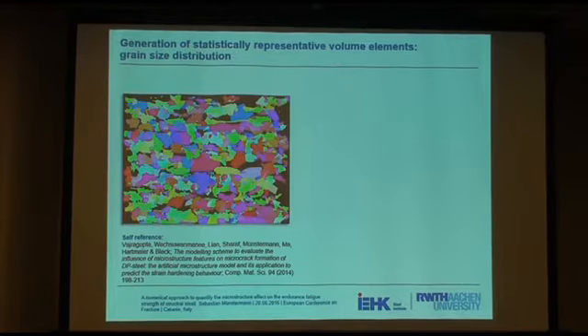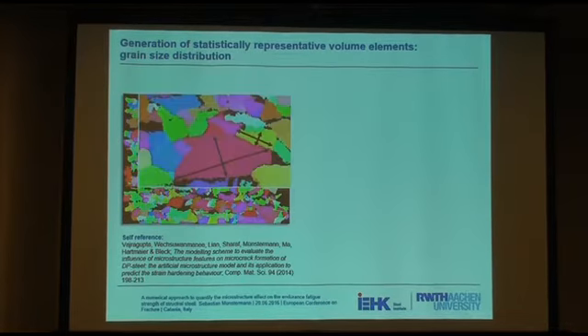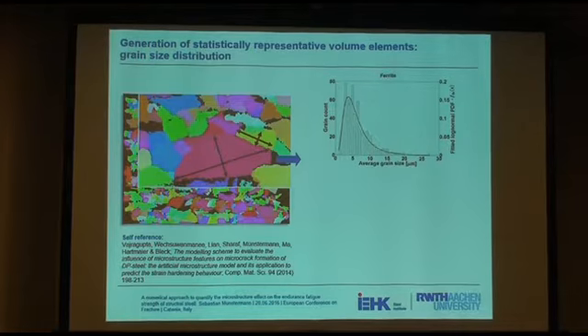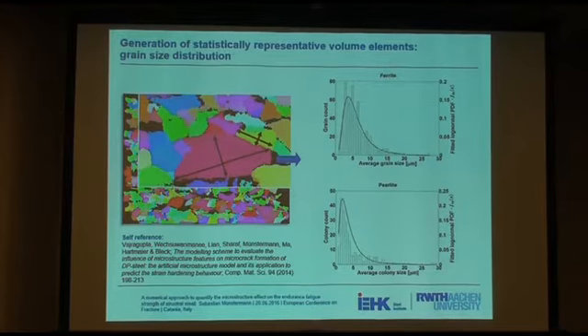Here you see an EBSD image of a typical steel of the grade S355. You can expect that the microstructure is made up of ferrite and pearlite. The colors here indicate the crystallographic orientations of the ferritic phase. First of all, you can measure the phase fractions for ferrite and pearlite, and then individually you can also measure the grain size distribution of the ferritic phase and of the pearlitic phase, and you can find suitable distribution functions to express these findings.